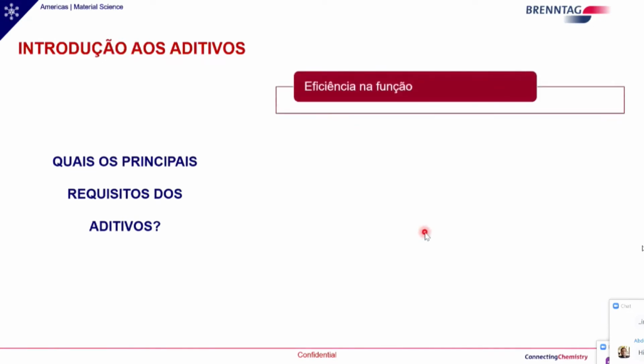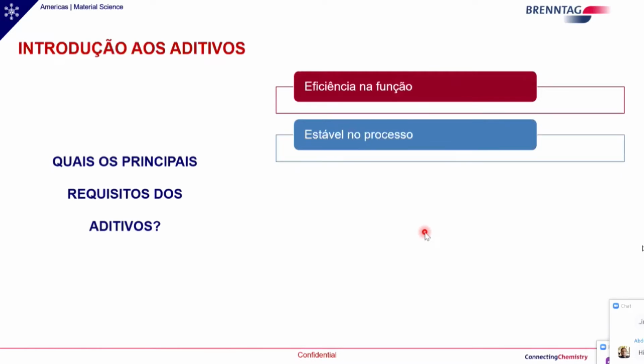The additives have to fulfill some requirements. The additives must be efficient in terms of their function. What is the function of an additive? Let us say that there are two different kinds of compatibilizing agents. Let us say that we have compatibilizing agent A, and in this case, we need a high dose of the component, 3% of the weight of the product, for example. And we have compatibilizing agent B. In this case, just at 2%, you are able to obtain the very same function and promote the very same benefits. So compatibilizing agent B at a lower dose is more efficient, right? It must be stable throughout the process. For example, if we work with the compatibilization of polypropylene and glass fiber, the process temperature can be very high, close to 270, 280 degrees, or even more than that, right?